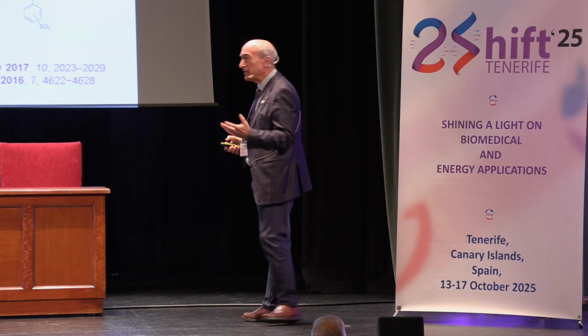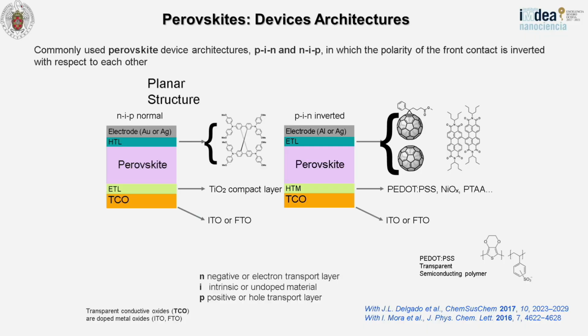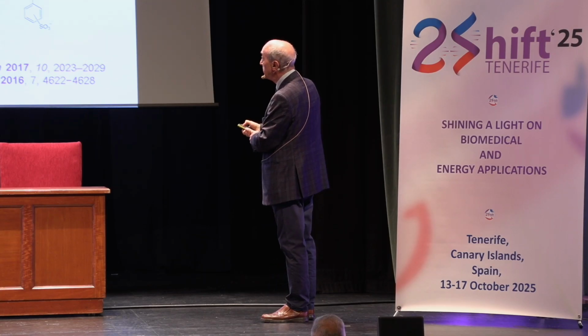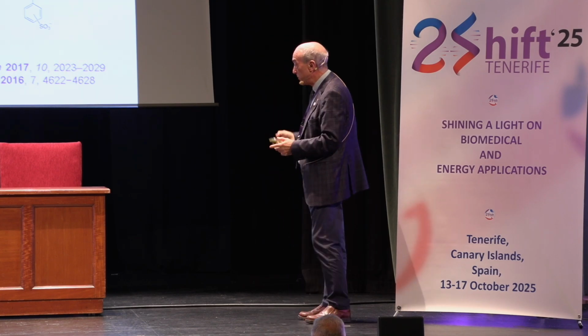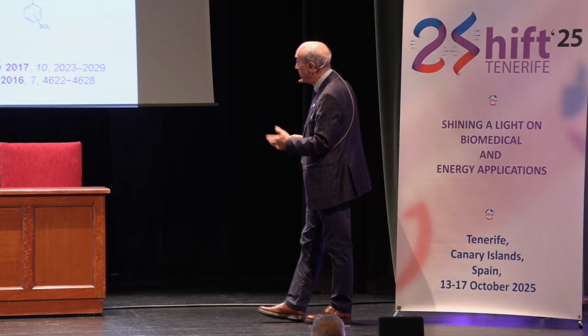So we have been very much interested in hole transporting layers along this time. But if you go to the reverse cell, then you have to change the order, and the hole transporting material is close to the transparent electrode. In order to keep the energy alignment, you have to change the materials. Here, with fullerenes or electron-accepting materials over there, and the electrode usually changes from gold to aluminum or silver.